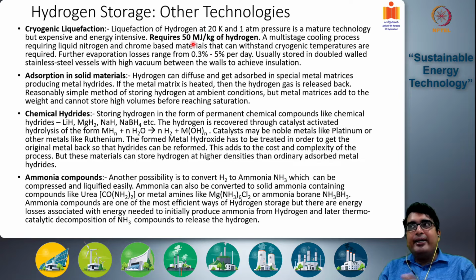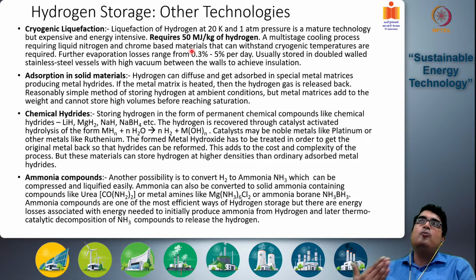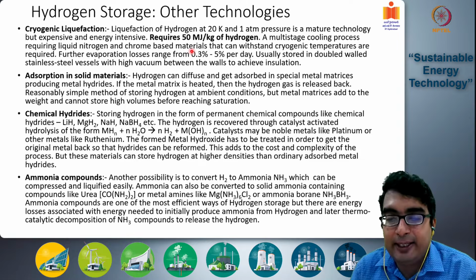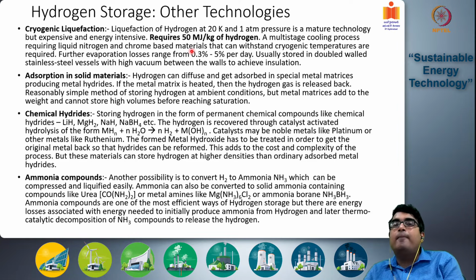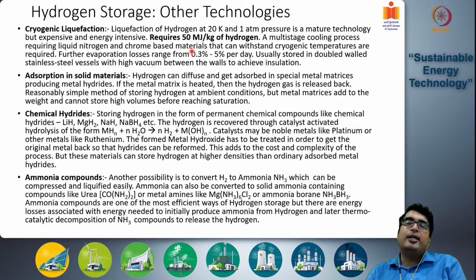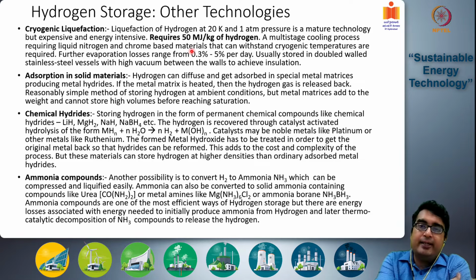It requires currently around 50 megajoules per kg to cryogenically liquefy hydrogen. Remember, the energy content of hydrogen is 120 megajoules per kg. So around 30 to 40% of that energy of hydrogen is being lost to cryogenic liquefaction itself, which makes it very difficult to make it commercially viable for energy applications. It is okay for space applications, but not commercially viable for energy applications at this stage. We can improve the technologies and decrease the energy required, and much work is going on regarding that.